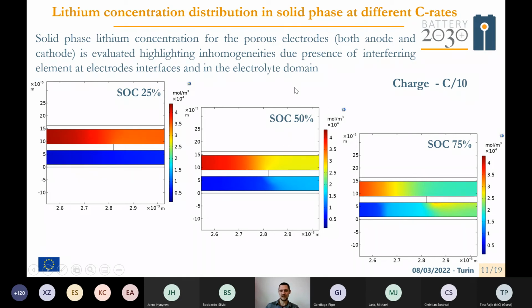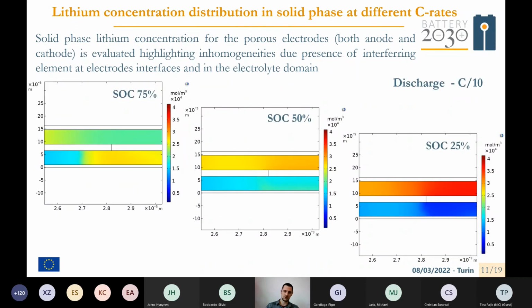During charge, the presence of interfering elements induces abnormal features in lithium distribution inside the solid phase. Here we report the same thing, but for the discharge part of the cycle, and you can see the behavior is basically similar to the previous one.